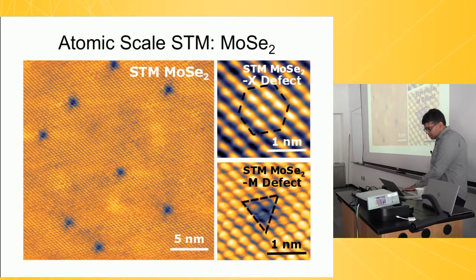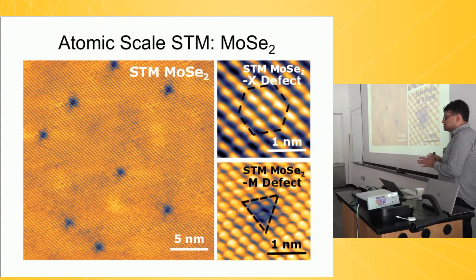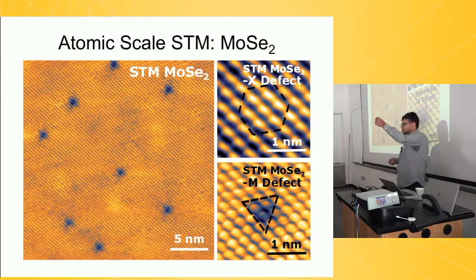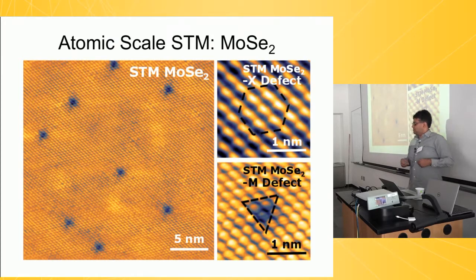And let me just tell you what we think these are. So I should say that in STM, we don't have any chemical specificity. So we have to use other things in order to help us understand what these things are. But let me tell you what these things are, and then I'll explain why. This thing we believe is a metal vacancy. It's just a missing metal atom. And this thing we believe is an anti-site defect. An anti-site defect is where there should be a selenium atom, but instead of the selenium atom, there's a metal atom sitting there.